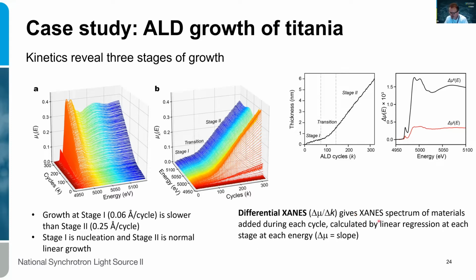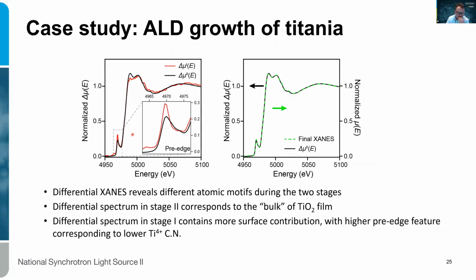And if we now introduce this differential XANES concept, which is nothing else but extracting from this kinetics the additions after each cycle. What are the spectra corresponding to the addition of the material from one cycle to the next? And if we integrate them or average them, those are the two spectra that we obtain from stage 1 and stage 2. And if you look closer at them, you see how this earlier step has a much stronger pre-edge feature, which is evidence for a lower coordinated titanium. Whereas the differential spectrum in stage 2 is really the bulk of titanium oxide.